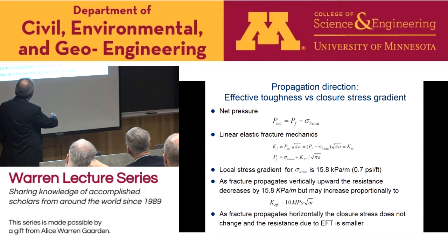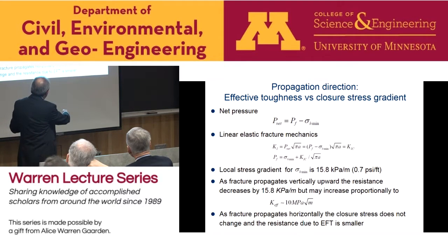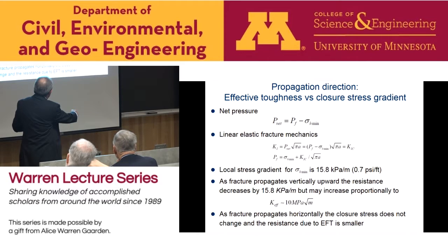Linear elastic fracture mechanics, uniformly loaded fracture. We have the stress intensity factor given by the net pressure times the square root of the half fracture length, and the fracture will propagate when we reach the K, the fracture toughness of the rock. When this parameter reaches this value, the fracture will propagate. We can solve this equation for the pressure in the fracture, which is equal to the closure stress, minimum in-situ stress, plus the fracture toughness divided by the square root of the fracture length. So the pressure in the fracture must exceed the closure stress and also this term.